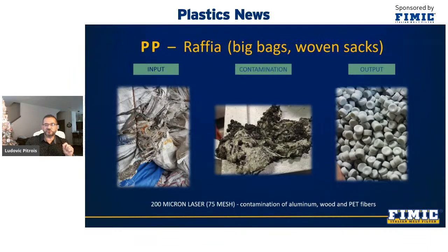Hence, the importance of good temperature control in the filtering area that is possible only if the pressure stays at a low level. We have many customers asking us to recycle this type of material, but it will only be possible with a good filtration process, but also an excellent crushing and washing system. In Colombia and Kenya, we have customers who only recycle this type of material to reproduce PP tapes again, with a percentage of recycled material sometimes as high as 50 to 70%, and applied filtration of 120 micron, 120 mesh, or even 100 micron, 140 mesh.